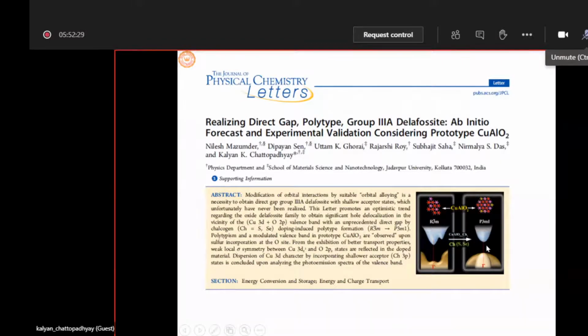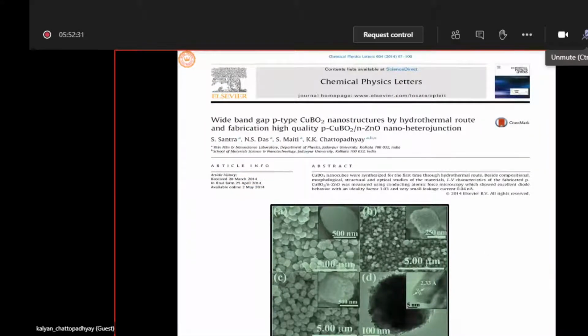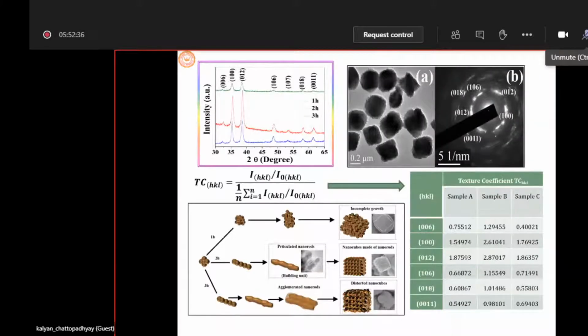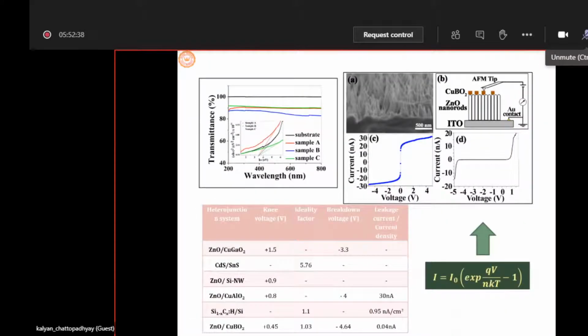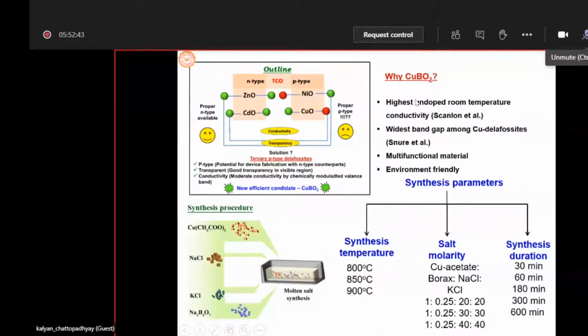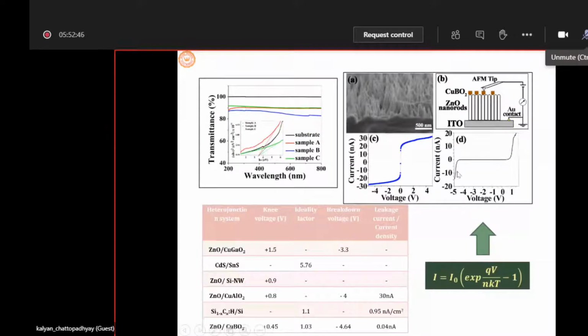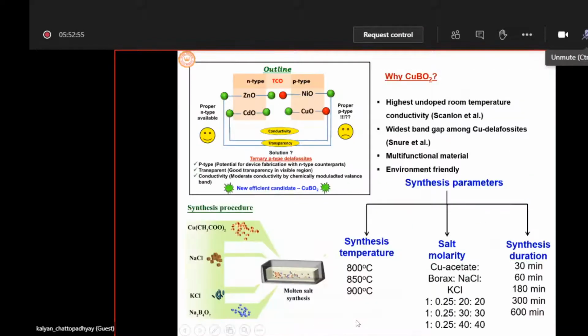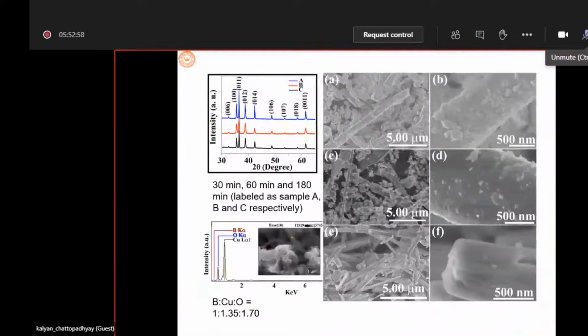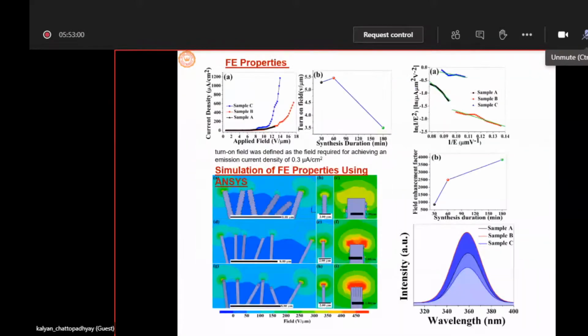Okay. Then we have extended this idea to other p-type systems like copper boron oxide, made a transparent junction with zinc oxide nanorod and copper boron oxide system, and obtained very good, for example, IV characteristics with an ideality factor nearly equal to 1.03. So these we have reported, and we have also reported interesting electron emission from such wide band gap semiconductor.